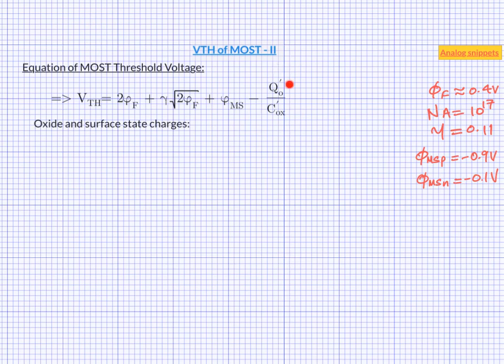This last term is in fact a collection of many different small effects. CMOS fabrication process uses many different chemicals at different stages, which tends to contaminate the gate oxide. In fact, this contamination was the reason that MOSFET was so difficult to fabricate in the early days. This contamination mostly contains the positively charged metal ions. These metal ions are also mobile, that means they move within the oxide depending on the applied potential. And this can introduce drift in threshold voltage with time.